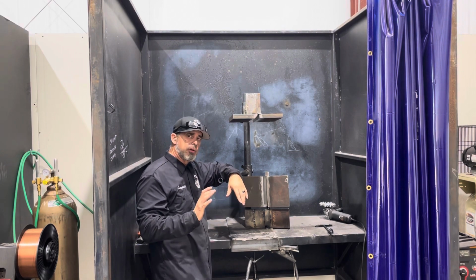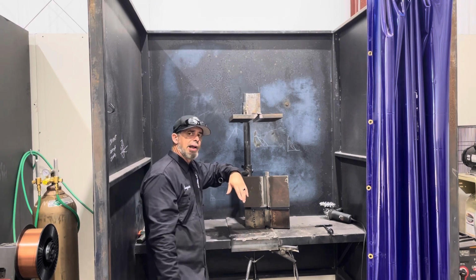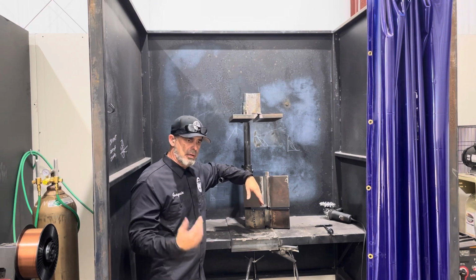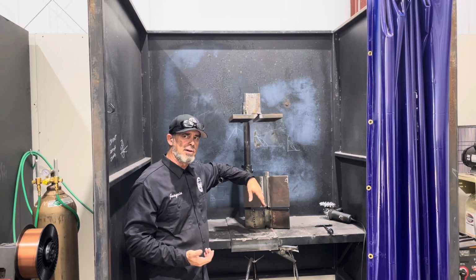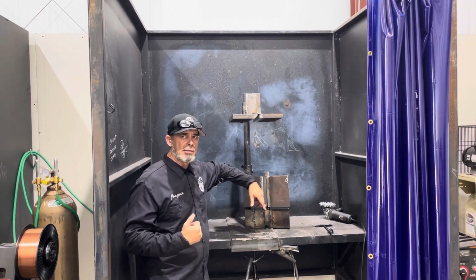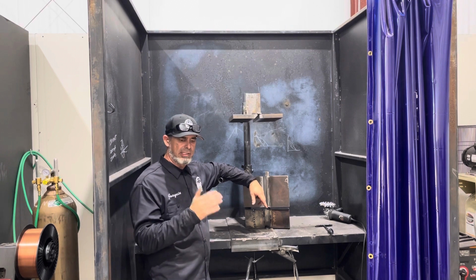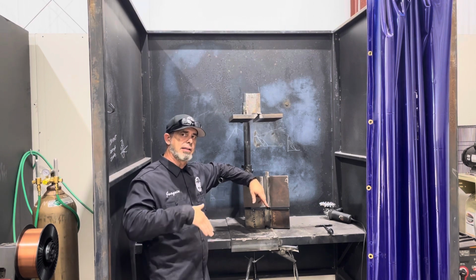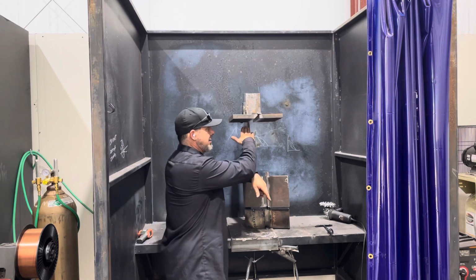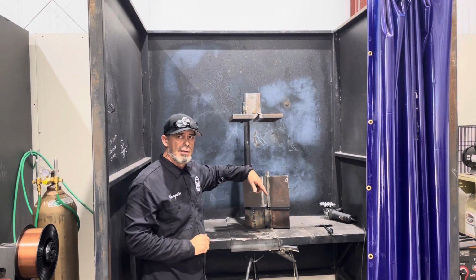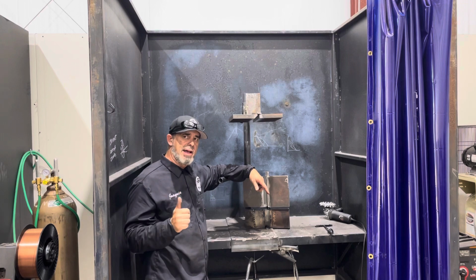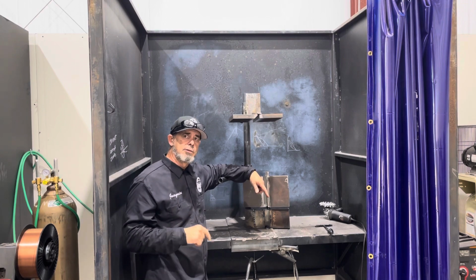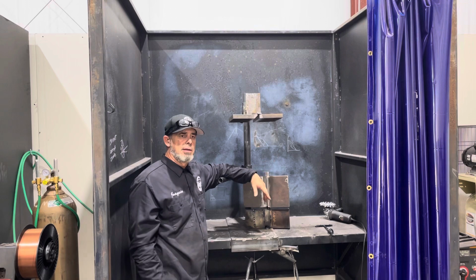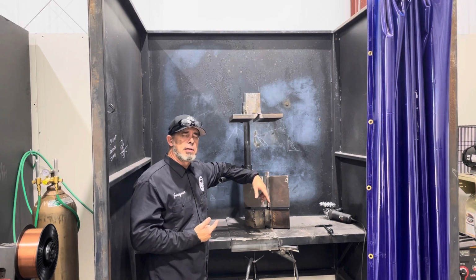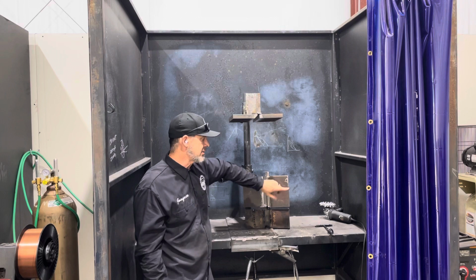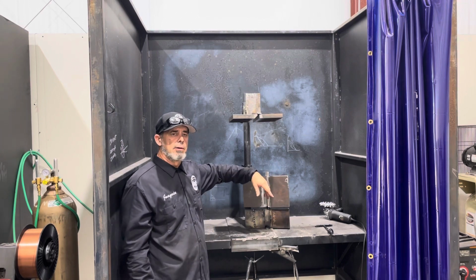Something that's very, very important, you guys. This is a dual shield wire. It's flux core and it's shielded with a 75-25 mix. You have to drag it. You have to have a drag angle, I'll say between 10 and 15 degrees. You're dragging that nozzle uphill and you're dragging that nozzle along the overhead. Very important, this is a drag. This is not a push. You're dragging it. Remember that old saying, if there's slag, you drag? Yes, you want to drag this. Very important to clean between the passes. I have my wire wheel ready to go.